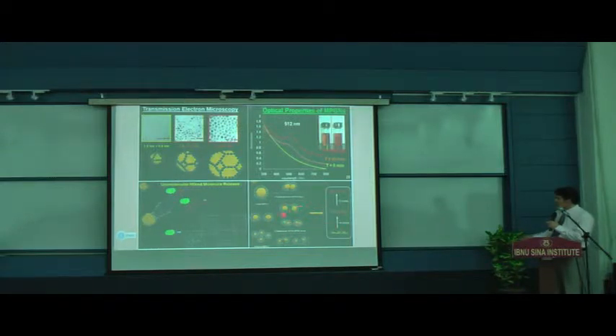If you focus here, we started with these small nanoparticles. We tried to release these molecules from the surface. As a result, they combine and attach together and make bigger and bigger particles. Also, we were able to calculate the stoichiometry of gold and organic component with the help of NMR and TGA and many other characterization techniques. So, based on this finding, we were also interested.